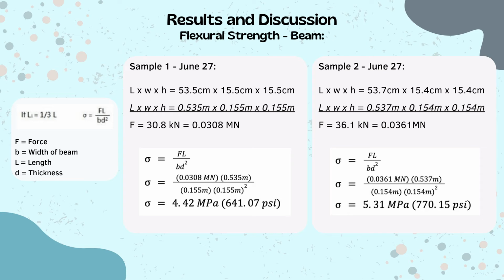For sample 1, we have here their dimensions of 0.535 meters by 0.155 meters by 0.155 meters, and their force is 0.0308 meganewton. Again, the units were converted to meters and meganewton to be able to achieve the final unit for the flexural strength. Here we have the calculation for the flexural strength for sample 1 equal to 4.42 MPa or 641.07 psi. For sample 2, we have their dimensions of 0.537 meters by 0.154 meters by 0.154 meters again, and their force is 0.0361 meganewton, and it is equal to 5.31 MPa or 770.15 psi.